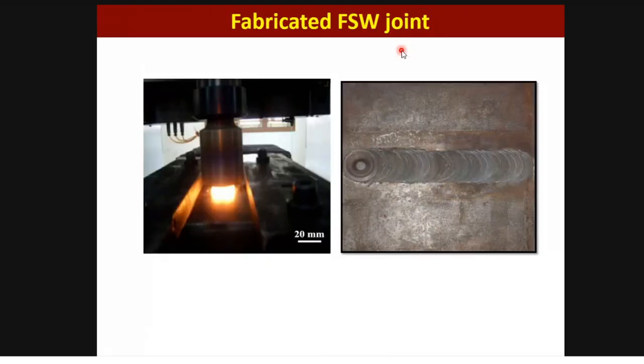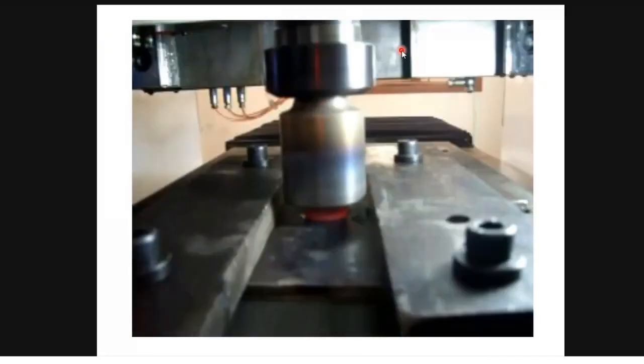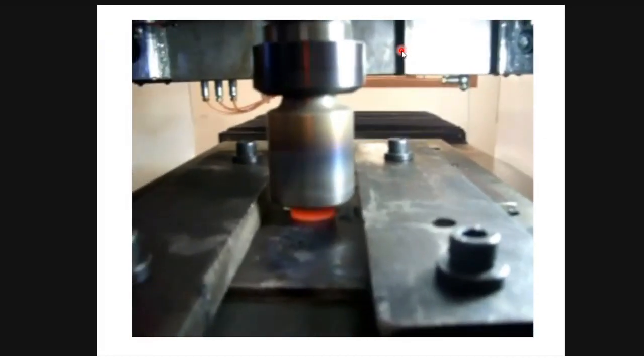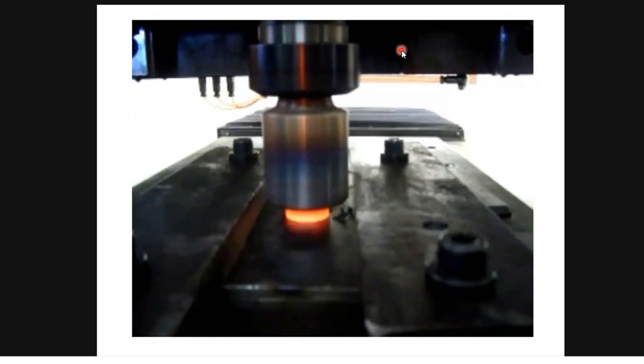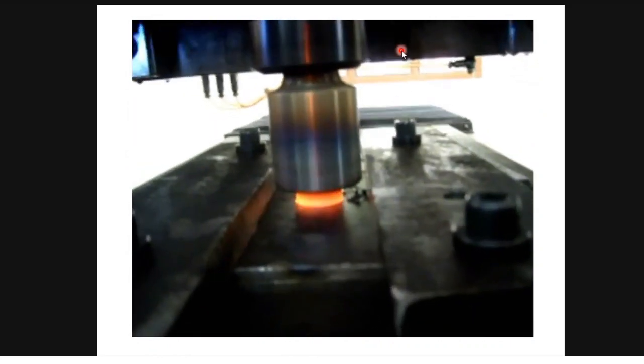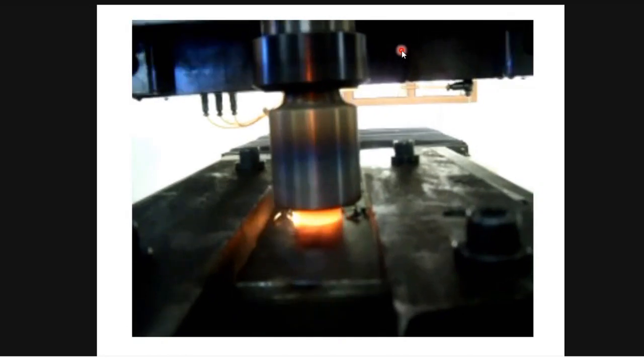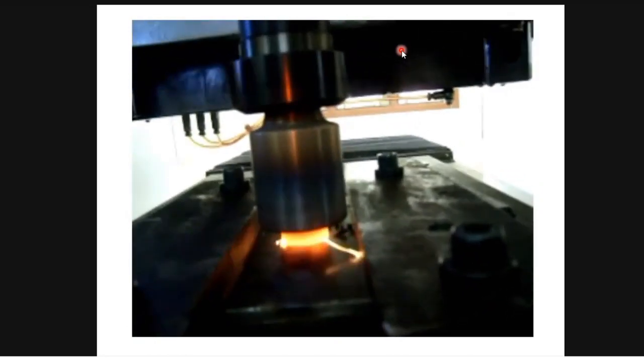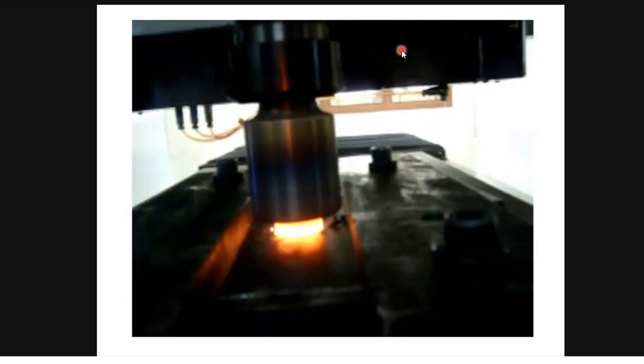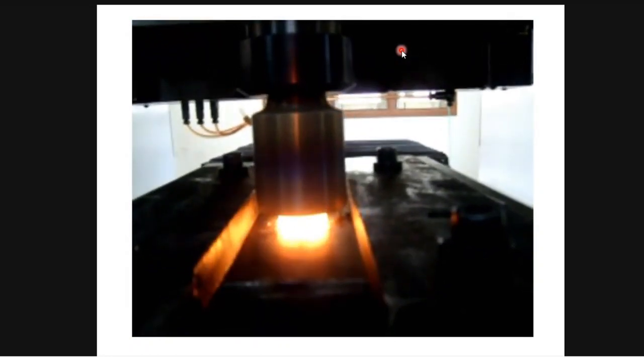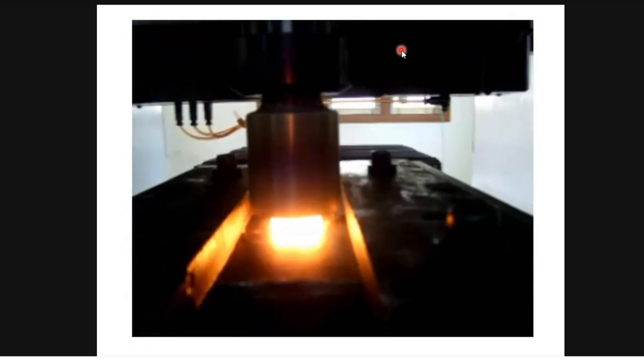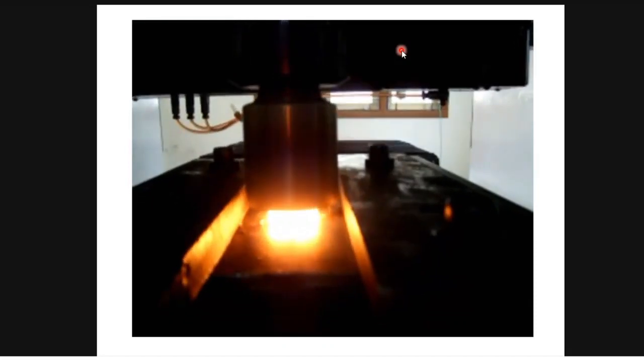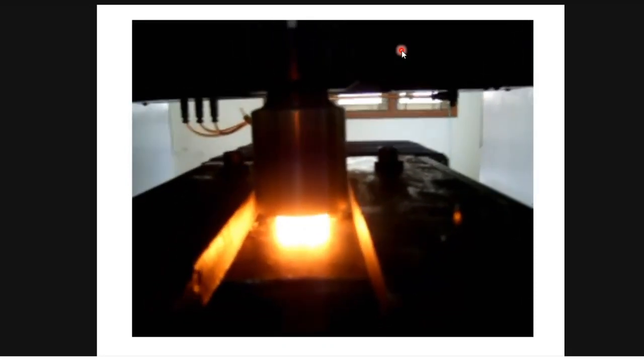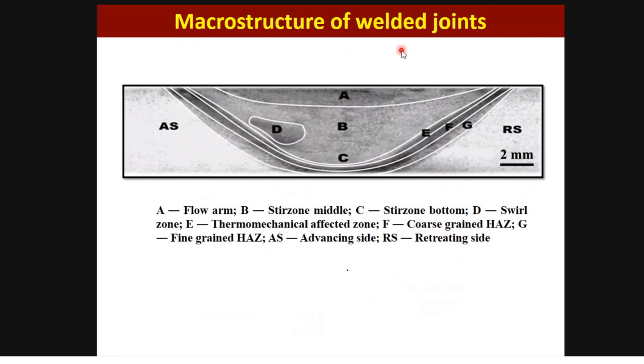And this is the photograph during the FSW, and this is the clipping. We used our machine, a CNC controlled friction stir welding machine, for joining this mild steel. So you see that the tool is undergoing a lot of stresses, and also the temperature is enormous. The temperature is something around 1100 degrees centigrade at that point. It's not melting there, but it is going to the red hot condition. So that's a great challenge. At that temperature and those forces, the tool material should withstand, keeping its profile, its dimensions, its geometry.